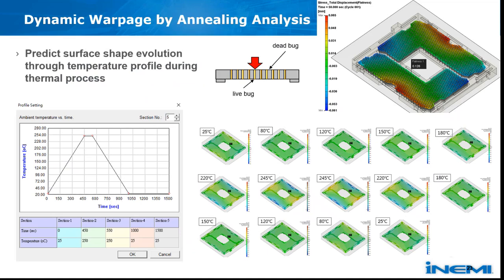So after the standard injection molding simulation, we perform the warpage analysis for the validation with thermal deformation measurement results. The molded circuit was exposed to a controlled environment temperature history based on the thermal deformation measurement. And the temperature distribution of the circuit was calculated at each time step and the warpage predicted at the desired temperature point. Then the surface shape and the flatness of the dead bug side of the circuit were estimated and compared with the measurement result.